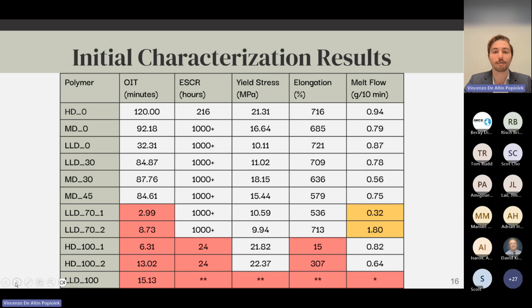For ESCR, which has an industry standard of 48 hours, we see that the linear low density polymers were able to significantly surpass industry standards, reaching over 1,000 hours, while the high density samples both failed at only 24 hours. We believe, however, that this was due to the high modulus which we saw in the high density polymers, and that by blending with a lower modulus polymer, we would still be able to consider these for blending and be able to surpass that 48-hour threshold.